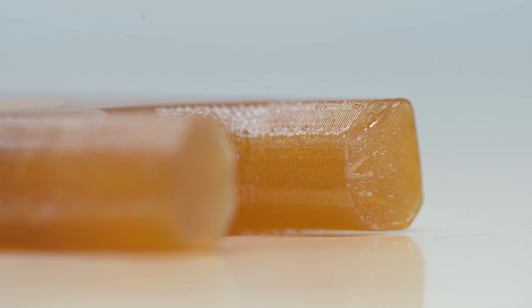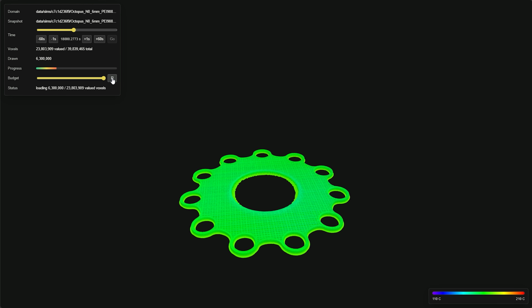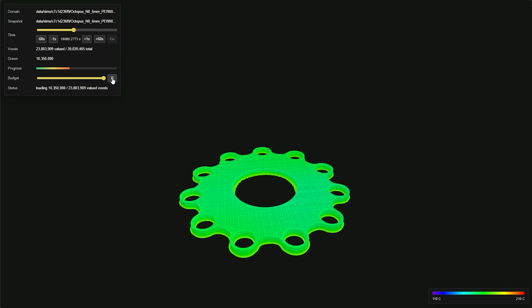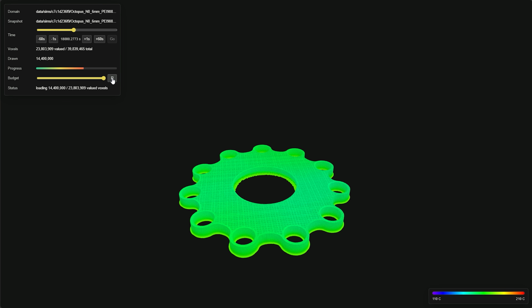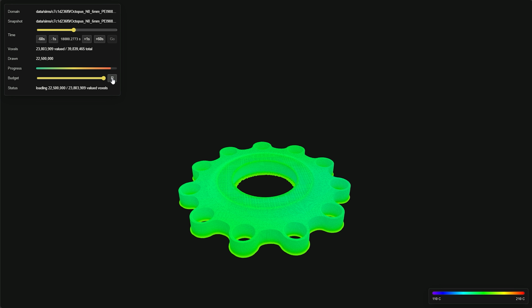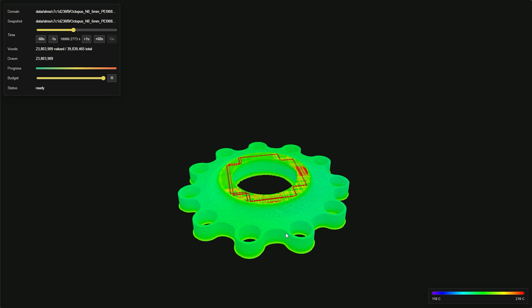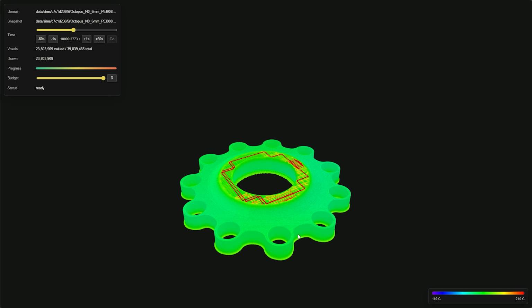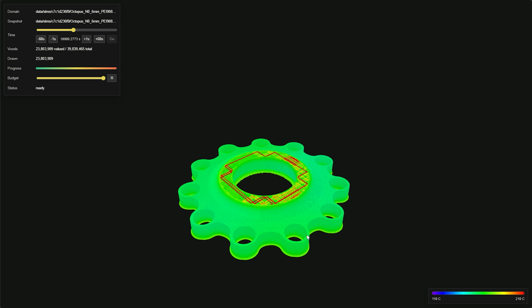To visualize this, we used our basis software to run transient thermal simulations of the build process, comparing parts printed at 120C with parts printed at 185C chamber. As you can see, on the 185C chamber, the entire part remains warm throughout the build, extending the welding window for each newly deposited layer.